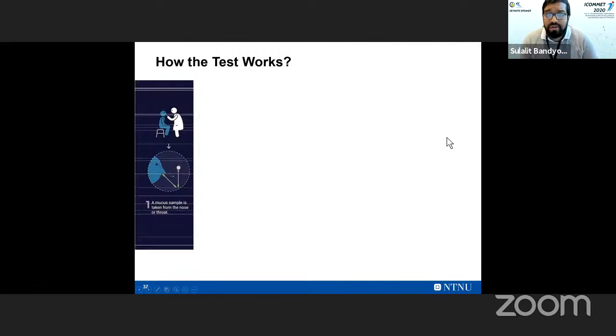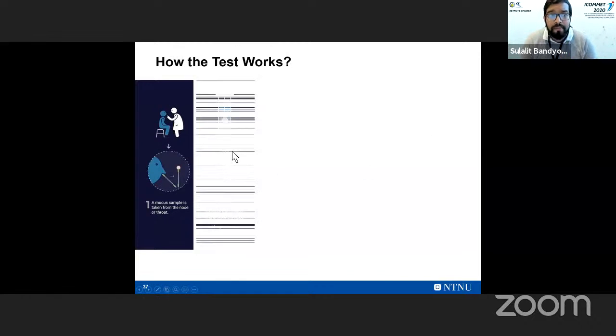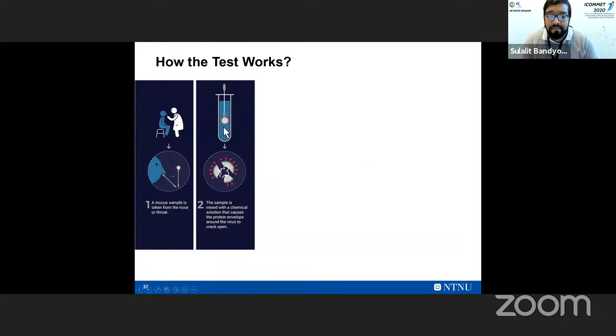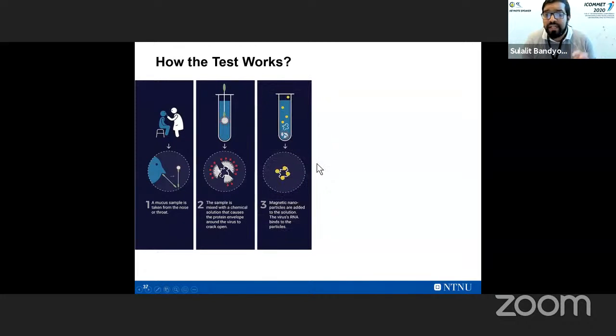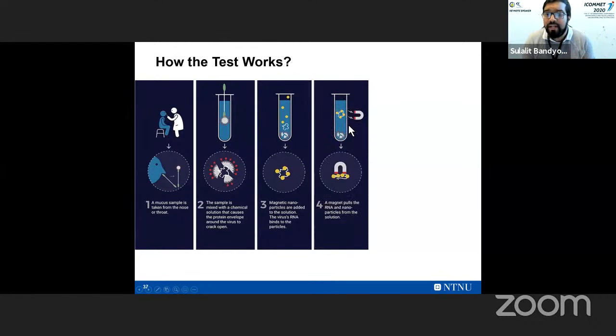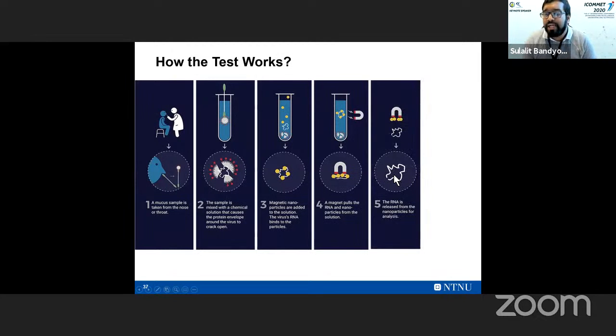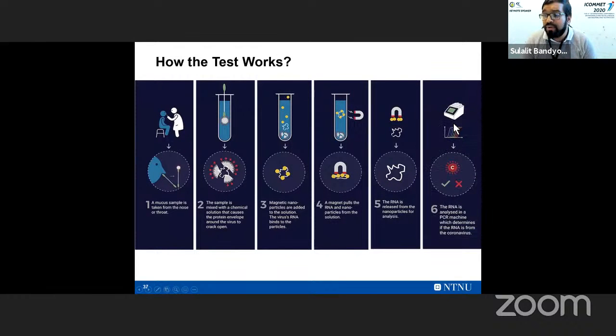How the test works, if you're wondering: this is a qPCR-based test kit whereby you take a nasal swab. The nasal swab is then put in a buffer solution, which breaks open the virus. The genetic material is exposed, and at this point, our magnetic nanoparticles are put in. They bind to the genetic material. You use a magnet to separate it out, so now the viral genetic material is sticking to the magnet. You elute it in a solvent, and then you use qPCR to find out if this is corona or not.